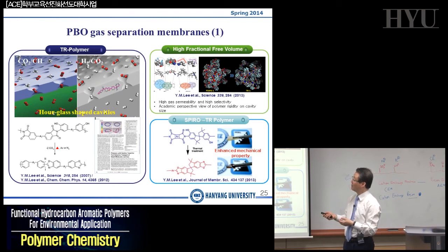What we have achieved was that we found this cavity, this pore, is in two sizes. What they call a bimodal distribution of those cavity sizes. We have smaller cavities and larger cavities, just like an hourglass. Hourglass. So we have a small cavity size of about 3.5 Angstrom. The large cavity size is about 8 Angstrom.